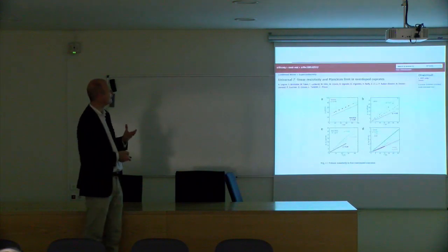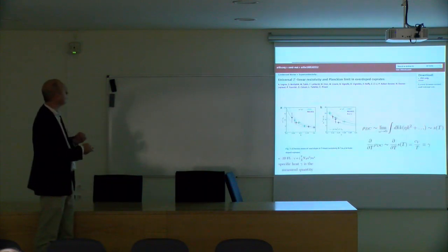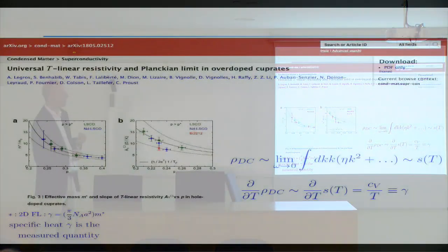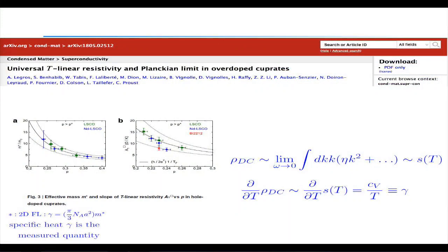If you look a little bit more precisely, you don't look at the scaling behavior, but the coefficient in front of it, it changes slightly with the doping. Well, if this story is correct, that also means that the entropy should change slightly with the doping. And in this experiment from last year, these people measured the specific heat in the system. The specific heat precisely gives you the coefficient of this linear factor.